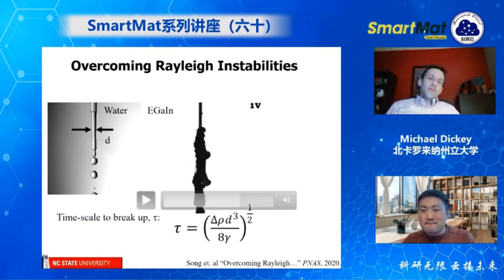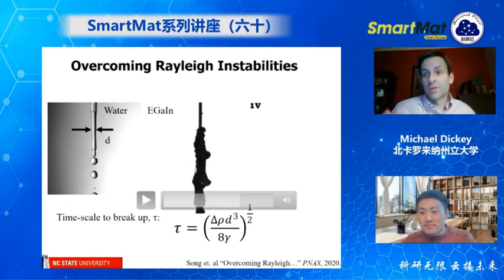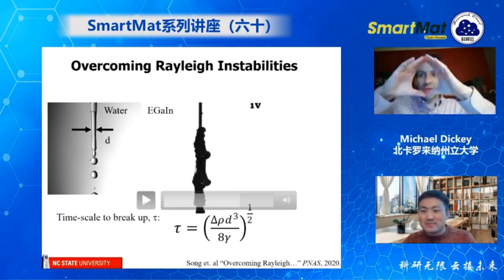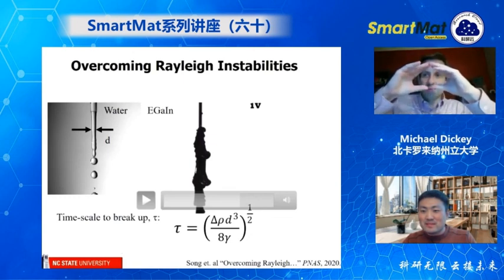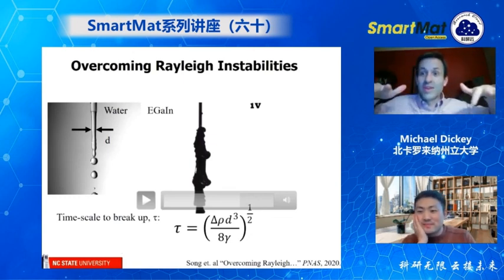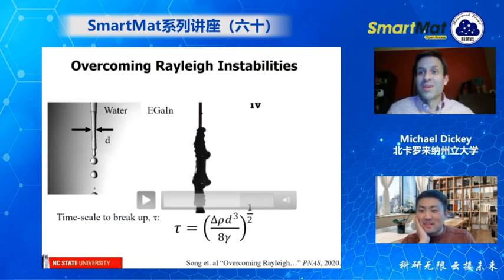Basically, this is driven by electrochemistry, and as you know, you need to achieve certain electrochemical reactions. You need to apply a certain potential, and because of that, the droplet size doesn't really matter up to a certain point. So to get the really interesting behavior, it's about 0.8 volts relative to the open circuit voltage. But again, the tension keeps dropping. If you look at the droplet as this happened, it gets flatter, flatter, flatter, and then suddenly it starts forming the fractals. Yes.